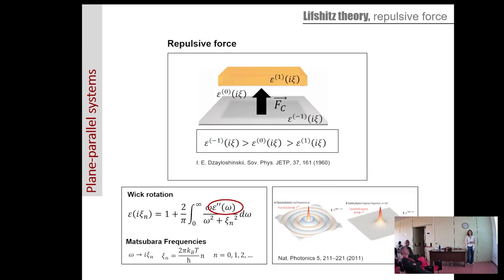So how can we get a repulsive force in a plane parallel geometry? It is not easy. There is this condition, equation, that the dielectric function of the substrate, the fluid, and the other material need to fulfill over a wide frequency range. This is a necessary condition, but it is not enough. So you just need to play a little. It must be satisfied over a wide frequency range, but it is not for sure that it's going to happen.